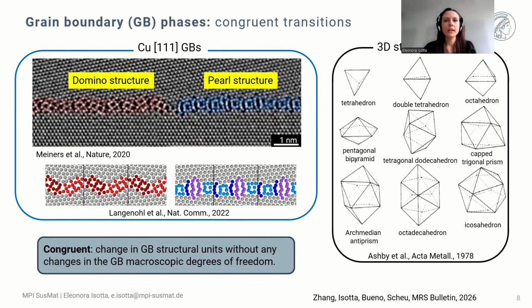And the interesting thing about congruent transitions is that we typically see this change in the structural units. With TEM, we see a two-dimensional projection of what happens in reality, so we need to keep in mind that these structural units are actually three-dimensional. It is of course difficult to reconstruct a three-dimensional unit, but this can be done with a combination of atomistic simulations, image simulation, and TEM observations.